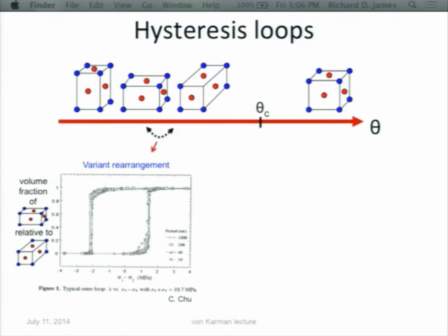And if you pass back and forth between this variant and this variant, which you can by applying stress, you see that this is some measure of the stress, and this is the measure of the volume fraction of this one versus this one. You can see that it transforms at a different stress going one way than it does in the other way. That difference defines the hysteresis, and it's a measure of the reversibility. And in fact, the area in this loop is the measure of the energy of your loading device